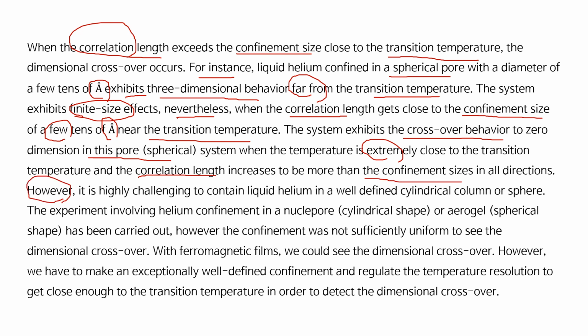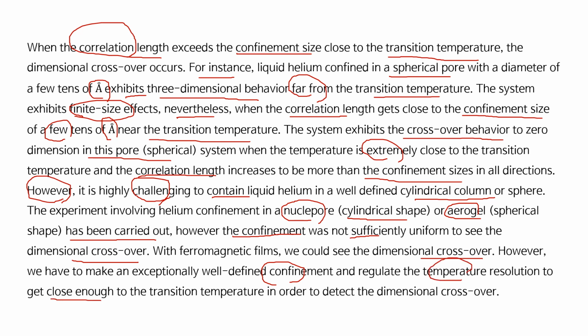However, it is highly challenging to contain liquid helium in a well-defined cylindrical column or sphere. The experiment involving helium confinement in a nuclepore, that is a cylindrical shape, or aerogel, that's a spherical shape, has been carried out. However, the confinement was not sufficiently uniform to see the dimensional crossover. With the ferromagnetic films, we could see the dimensional crossover. However, we have to make the exceptionally well-defined confinement and regulate the temperature resolution to get close enough to the transition temperature in order to detect the dimensional crossover. So it is very hard to observe the dimensional crossover in the helium system or other systems.